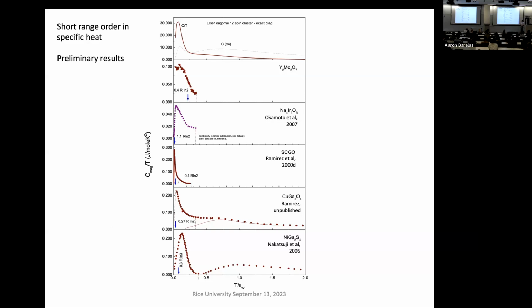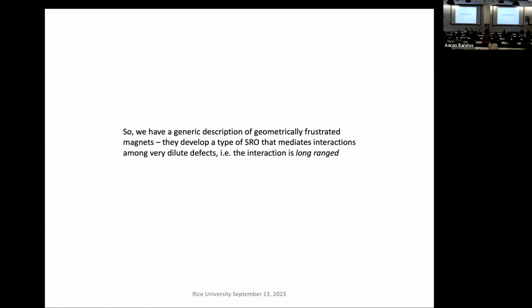There's a paper on copper gallium oxide, which claimed, based on measurements only done up to this point, that there was zero-point entropy. But I measured it up to higher temperatures and recovered the entropy. So we need more measurements here, but it's looking like this hidden energy scale represents the loss of the majority of the spin entropy on cooling. So the interaction must be long-range if it's showing spin glass behavior at arbitrarily low temperatures.